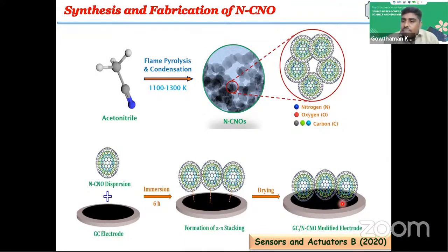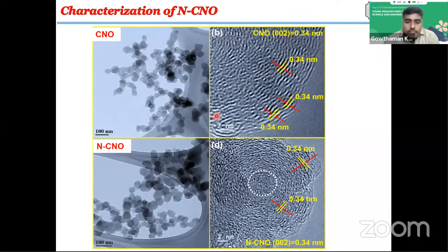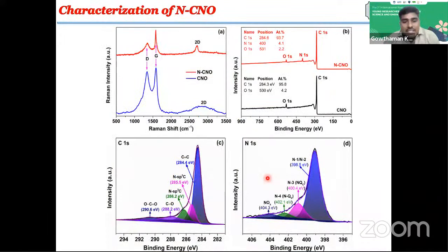It is a very graphitic structure with concentric rings like onions, confirming the formation of carbon nano onions. It was characterized by HRTEM images of the CNO and nitrogen doped carbon nano onions. The N doped carbon nano onions give an sp2 hybridized material with concentric rings like onions, so the name comes from that. And it was characterized by Raman and XPS also. The presence of nitrogen groups is confirmed from the N1s spectra, and the D by G ratio confirms the sp2 hybridized, highly graphitic carbon material.